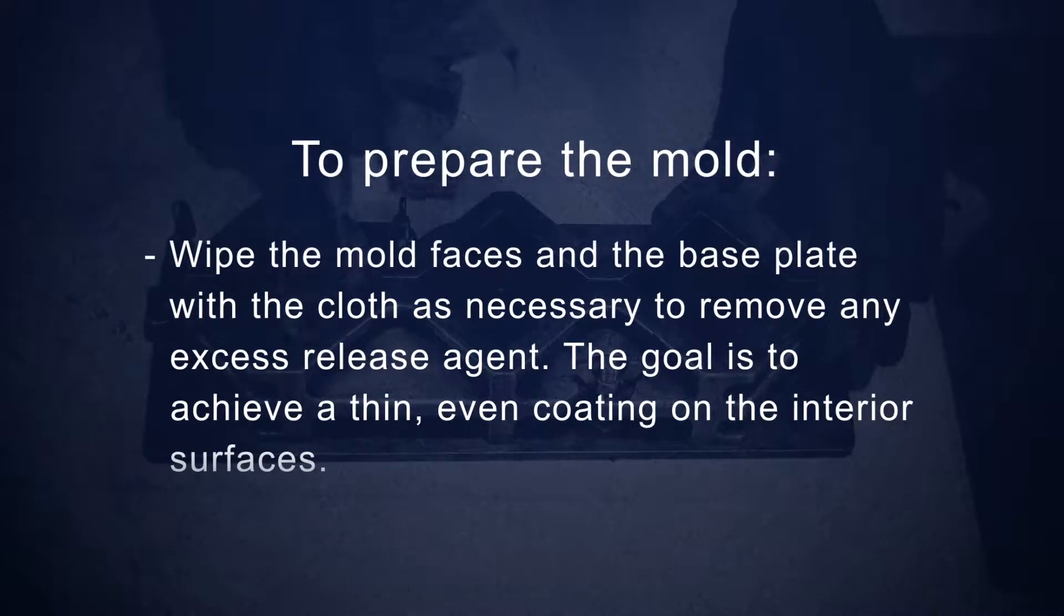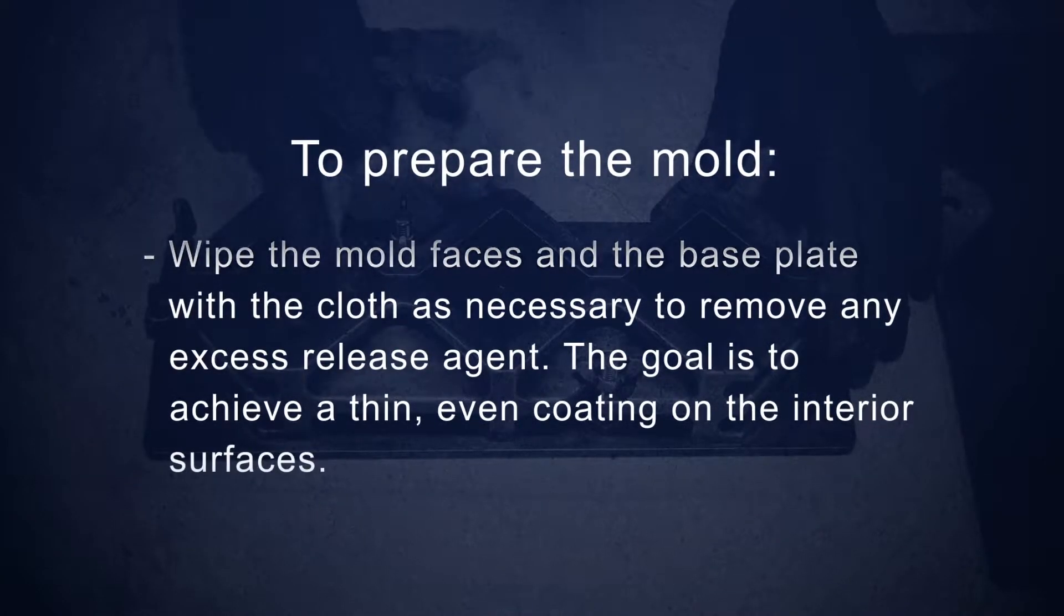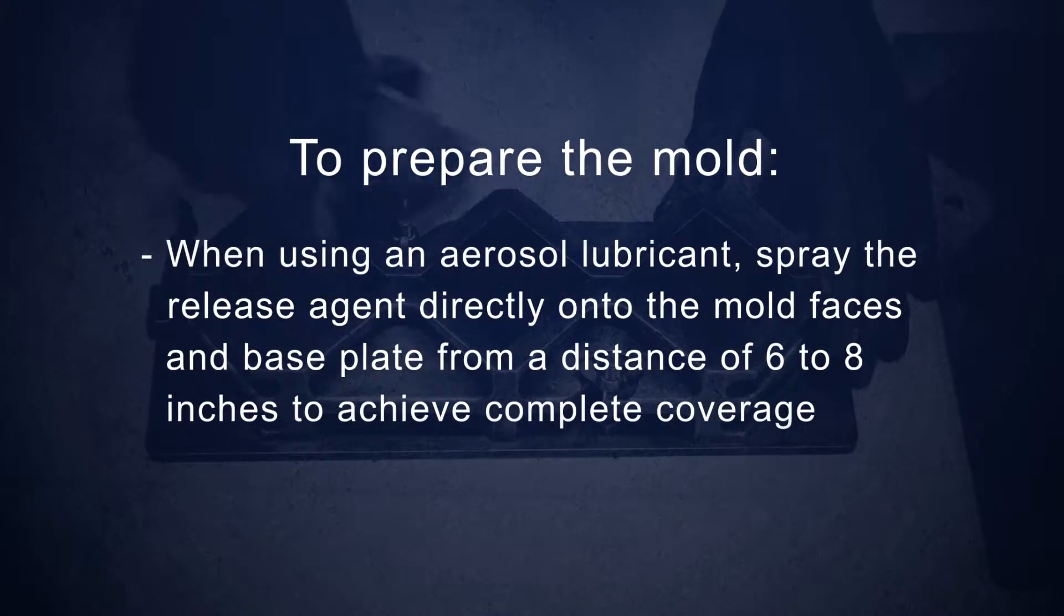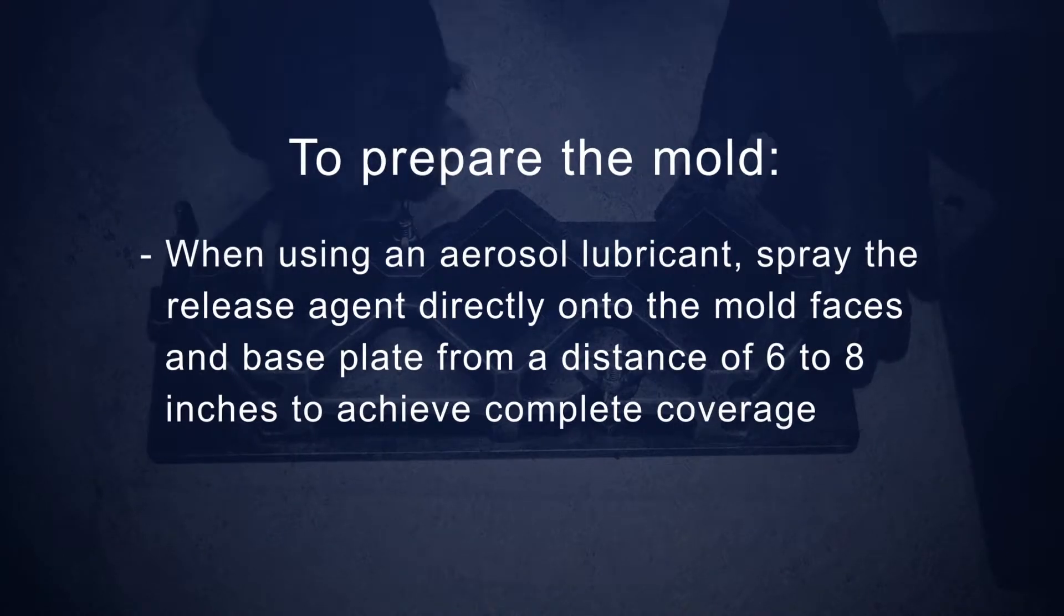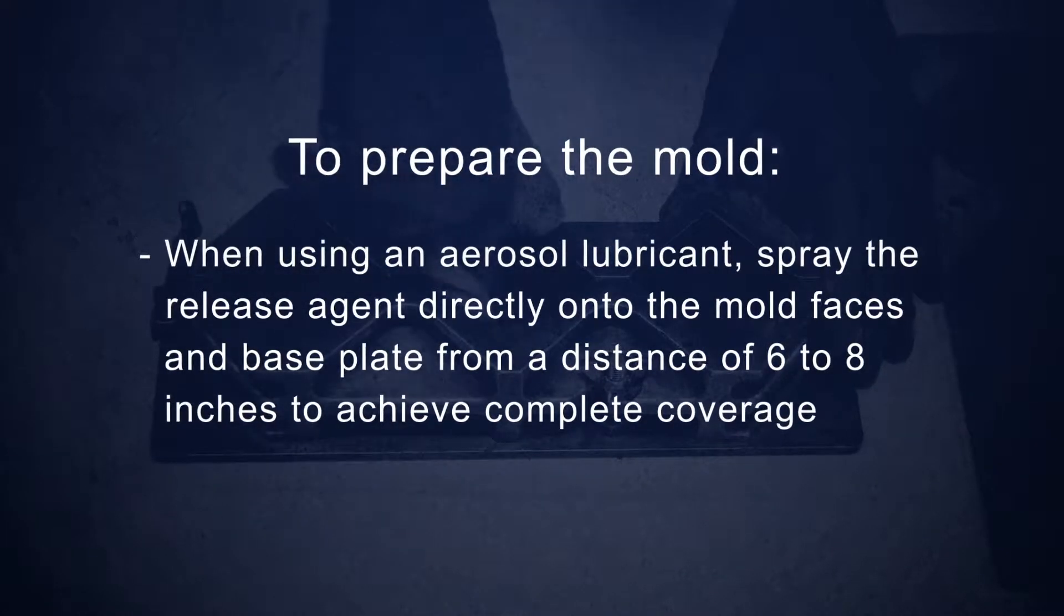The goal is to achieve a thin, even coating on the interior surfaces. When using an aerosol lubricant, spray the release agent directly onto the mold faces and base plate from a distance of 6 to 8 inches to achieve complete coverage.